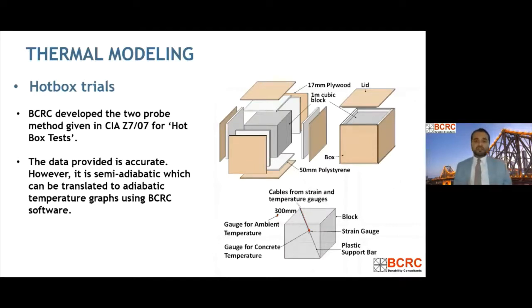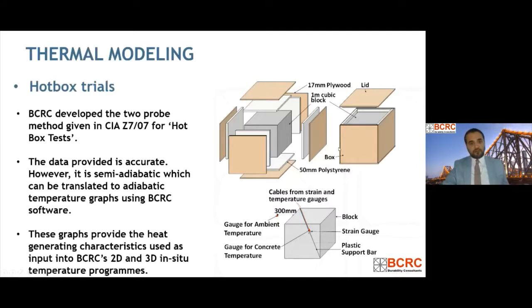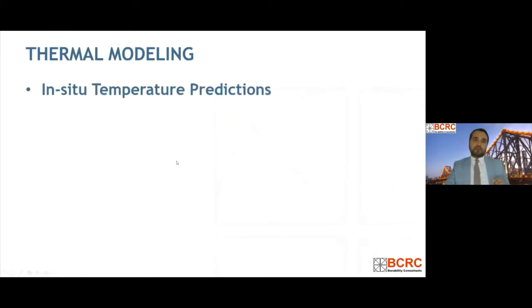You cannot use that data simply in your modeling because this is a semi-adiabatic test, and you have to change this data to fully adiabatic, and we can do that at BCRC using our in-house software, which changes the semi-adiabatic data to adiabatic. And then once you get that adiabatic curve, from the graph, you can then generate the heat generating characteristics of the concrete, which then can be used in 2D or 3D modeling to predict the in-situ temperatures, right?